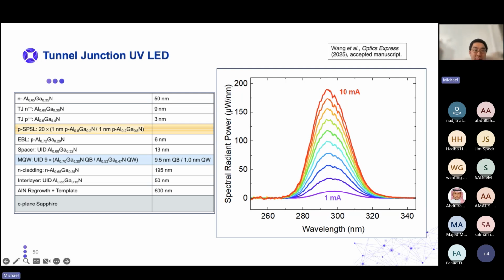Because the higher doped N-type aluminum gallium nitride that we typically would want as a contact layer would not allow for a quick test. So the quick test works because you can put on an indium on a scribed contact that cuts through all of these layers, and the current will flow through the path of least resistance. And if all the layers on top of the bottom N cladding are not conductive, then the current will preferably flow through the N-type cladding material. And that's why our quick test works for normal LEDs, because the p-type material is all very non-conductive, relatively speaking, compared to the n-type material.